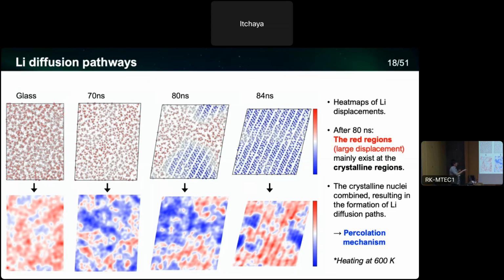And when the alpha phases are connected laterally or vertically, new lithium migration paths are formed, which further enhance the lithium migration. If you look at the activation barrier, the degree of decrease in the activation barrier is enhanced when we have the connected crystalline regions. This is also the same as the experimentally proposed mechanism, that is, the percolation mechanism. So through these calculations, we can reproduce the percolation mechanism when we heat it at 600 Kelvin.